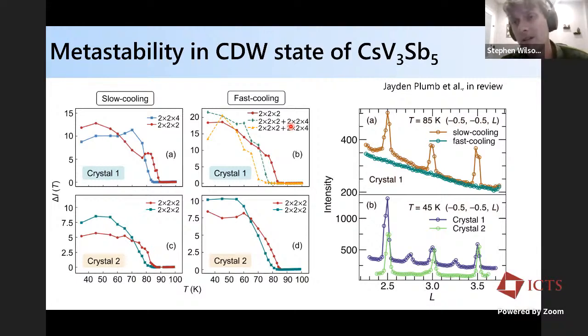Now to the question about, do we see different energy scales? Oh yeah. If you take a fixed cooling rate in the cesium system, and we're not the only ones who have seen this, there's another group that's seen this. If you cool through the CDW and you look at the onset of charge order via diffraction at different wave vectors, with different out-of-plane wave vectors, so same in-plane wave vector but different out-of-plane wave vectors, you see the onset of charge order at slightly different temperatures. They can be as far spaced as 10 Kelvin or something, depending on how fast you're cooling. So that sort of stages in,